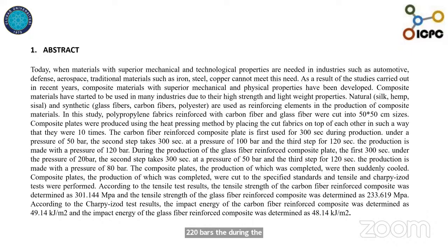During the production of the glass fiber reinforced composite plate, we had the first cycle for 300 seconds at a pressure of 20 bar, the second cycle for 300 seconds at 50 bar, and finally, at the third step, 120 seconds at 80 bar pressure. After the production of the plates, the samples were suddenly cooled and production was completed. The plates were cut to the specified ISO standards in order to perform the tensile and Charpy investigations.